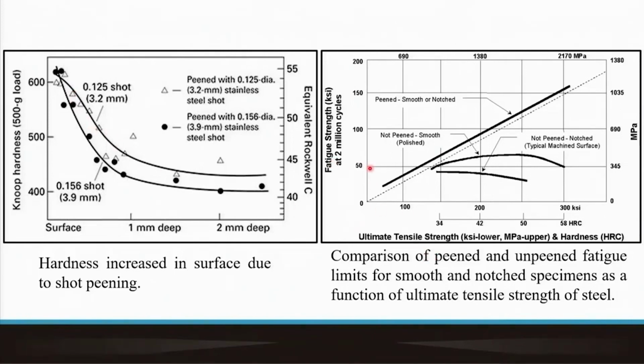Okay. Similarly, when you are doing similar operations with multiple prior deformation or prior history, let's say this particular curve is when the material was not peened and had a notch, so the failure under fatigue will be much faster and will show a much lower fatigue strength. On the other hand, this broken line is basically the normal curve, the typical strength behavior expected. And as you can see, the material which is peened, which has been subject to shot peening, and hence the surface is smooth or notched, in either case, will show a greater fatigue strength.